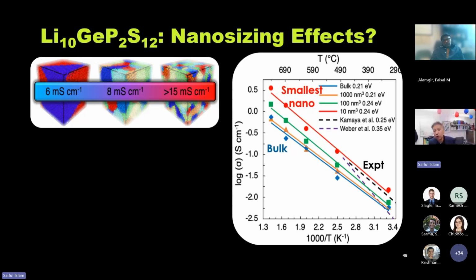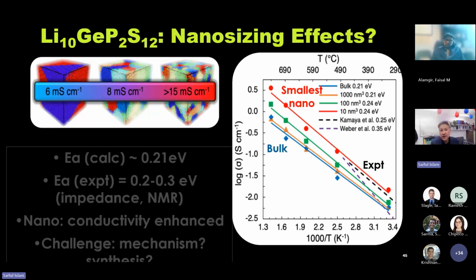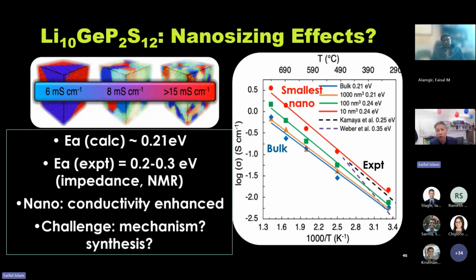But more importantly, the simulations predict that the conductivity would increase threefold by going down to the nanoscale. The calculated barrier is about 0.21 electron volts. The experimental bulk values range from 0.2 to 0.3 electron volts from impedance and NMR measurements. So the important result is the conductivity is enhanced by going down to the nanoscale. So that's a clear prediction. But this presents a challenge.